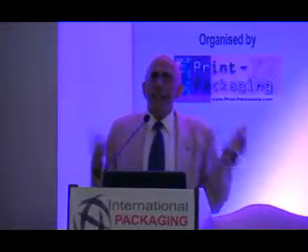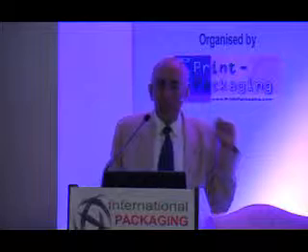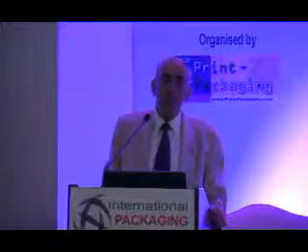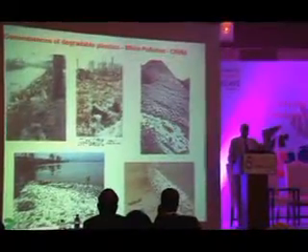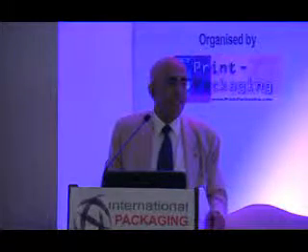Now, why do we need complete biodegradability and what the problems could be? This is the consequence of degradable plastics. They in China call it white pollution. And they didn't go to just making degradable. In China, if you remember, all those mulch films were made very, very thin. So it would simply break down. When it breaks down, as you all know, polyethylene density is less than 1. It flies all over the place. And so you have these collections of plastic dust in places where there's not even humans there. And these pictures are then used by NGOs to show you how bad the plastics industry is. So you are your own worst enemy, right?